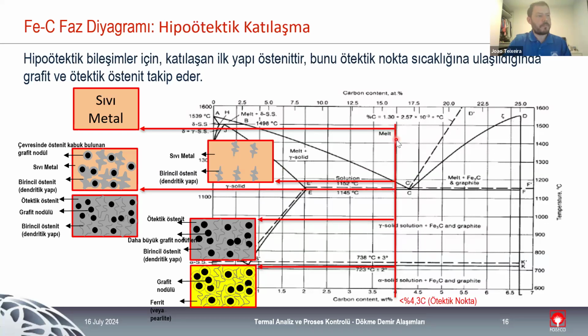And we can see that we are going to lose temperature. We have a point here. It doesn't matter the percentage that we are going to have for carbon, and they are losing temperature. And when we reach the liquidus temperature, so when we reach the point where we have a mix of liquid and semi-solid state, the first semi-solid state phase to solidify is austenite. So we have liquid metal and we have austenite being formed. And we are continuing to lose temperature. And when we reach the eutectic level, at 1151, 1152, around these temperatures, we have the start of the graphite phase. So after this point, we have a mix of austenite and graphite being formed. And this is what happens until we have the cast part solidified.